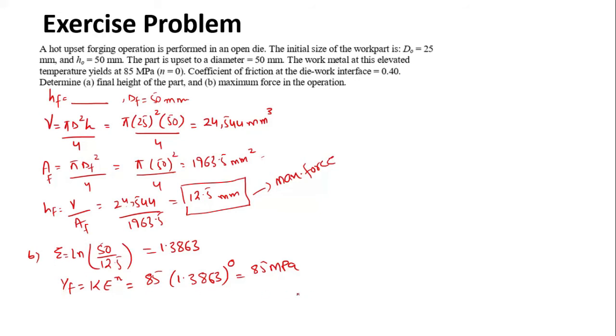So the maximum force, as we know, occurs towards the end of the stroke, so we will simply find out the forging force equals Kf Yf into A. We know the cross-sectional area, that is equal to this one. We have the flow stress. The only thing we need to determine is the shape factor, that is equal to 1 plus 0.4 into friction coefficient into diameter divided by height.